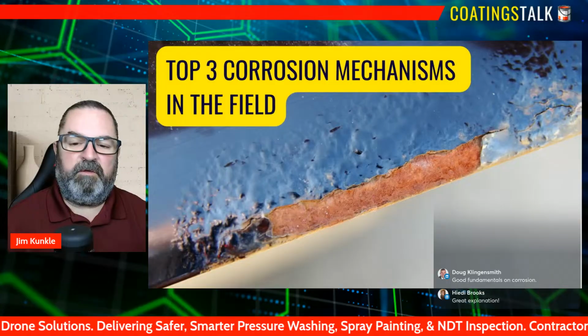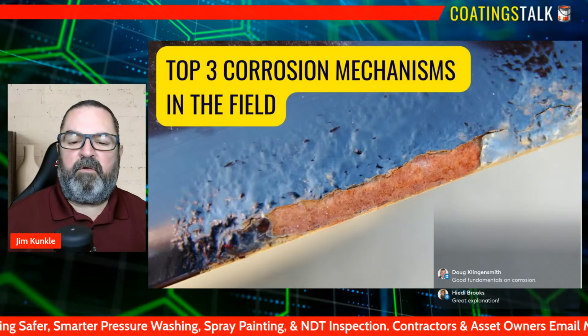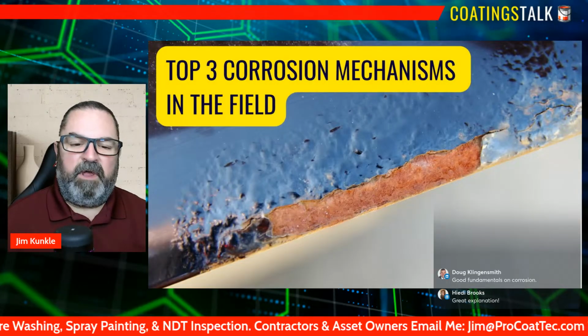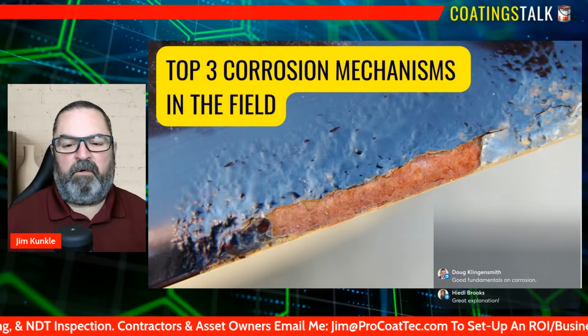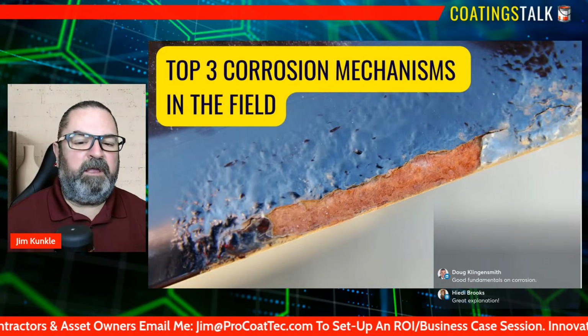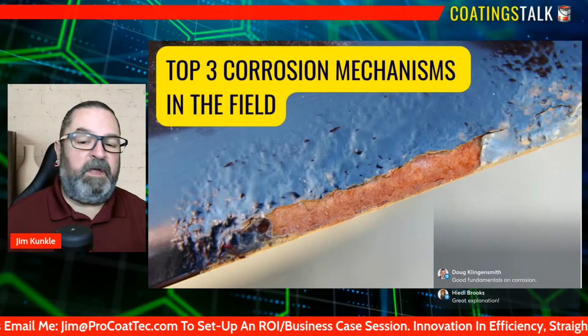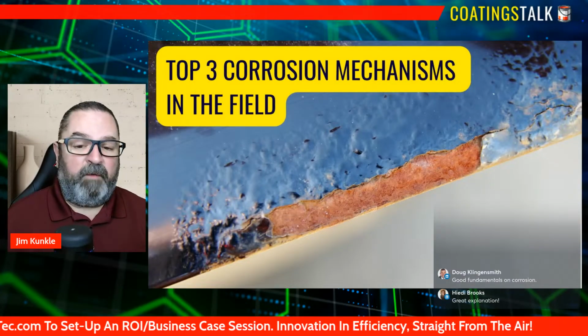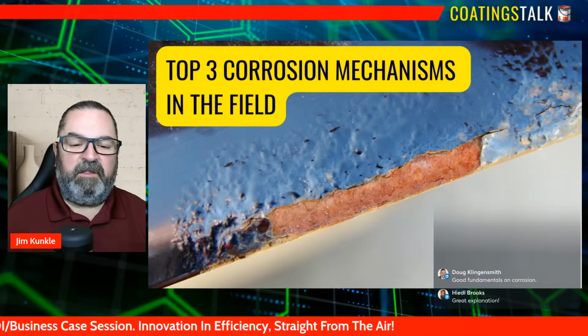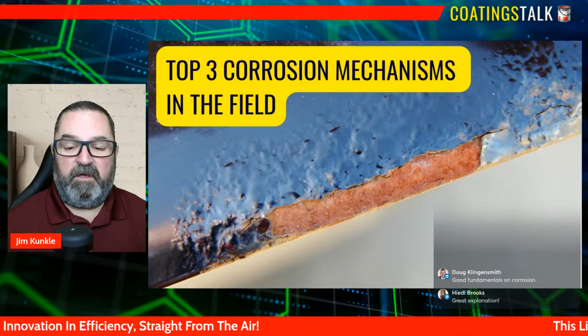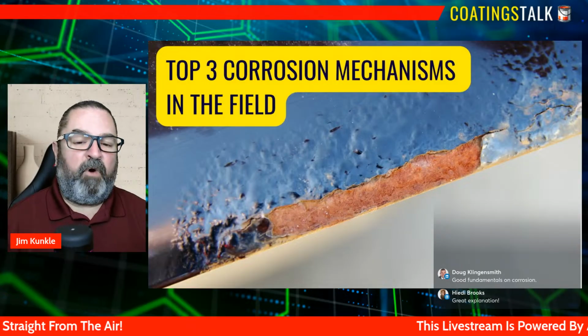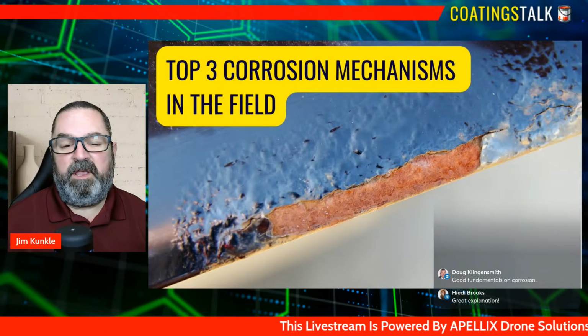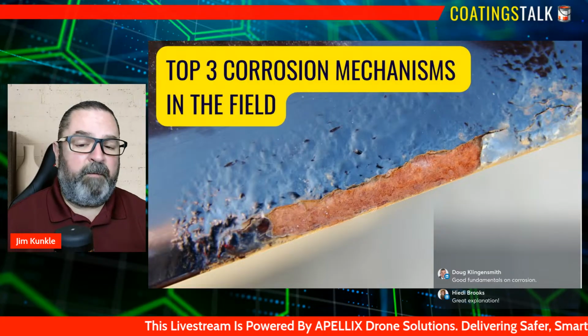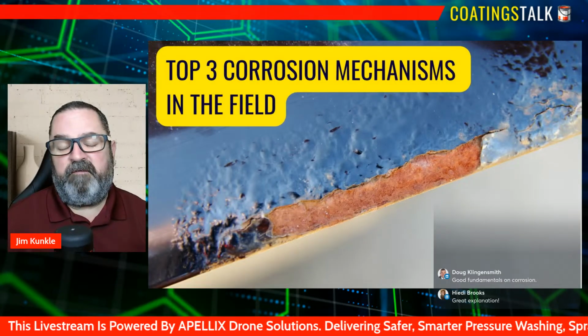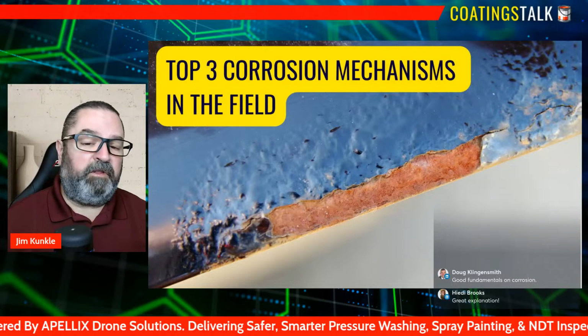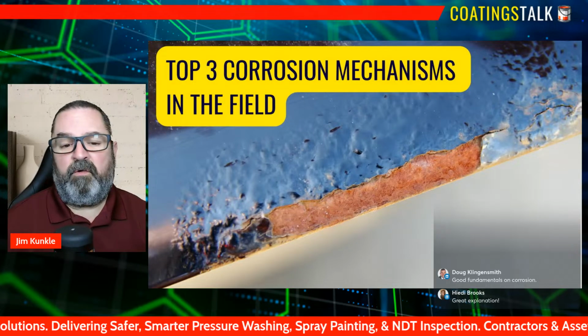This mechanism occurs when the entire exposed surface of a metal corrodes at roughly the same rate, and it creates a widespread, even layer of metal loss. To the untrained eye, it may look like a simple, uniform rust film and nothing dramatic, nothing localized, nothing alarming, but that broad, consistent attack is quietly thinning the metal everywhere at once. Over time, this steady reduction of wall thickness can compromise structural integrity. It can reduce pressure handling capabilities and also shorten the service life of tanks, of pipes, and things that support other critical components.